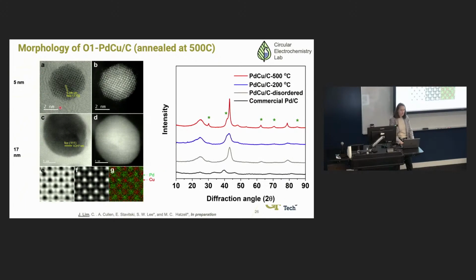As you can see, we looked at different size nanoparticles from 5 nanometers to 17 nanometers. These TEM images were exciting to us because they really do show that you have a high degree of ordered copper and palladium in your catalyst. Again, you can see the highly ordered degree of the catalyst here. We could also confirm from XRD that we were getting the highly ordered catalyst that we wanted.